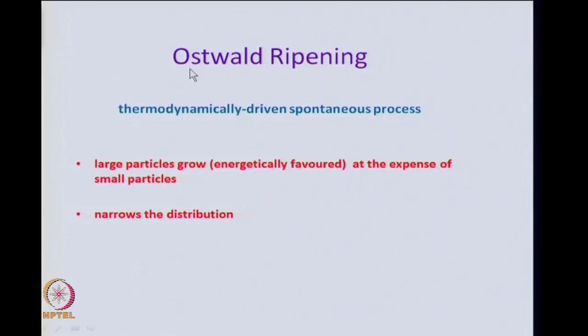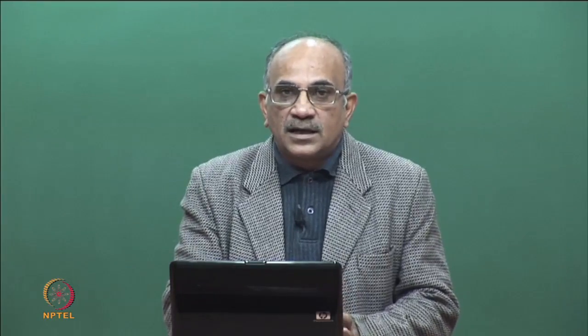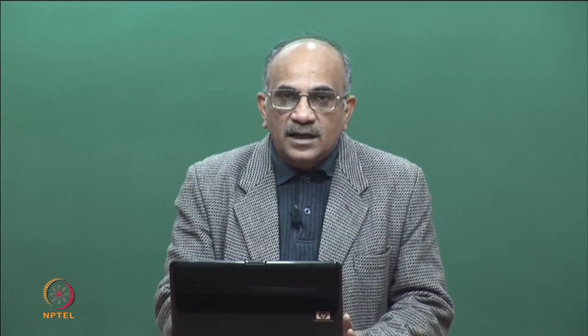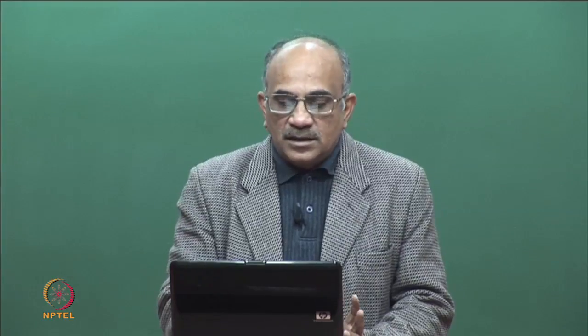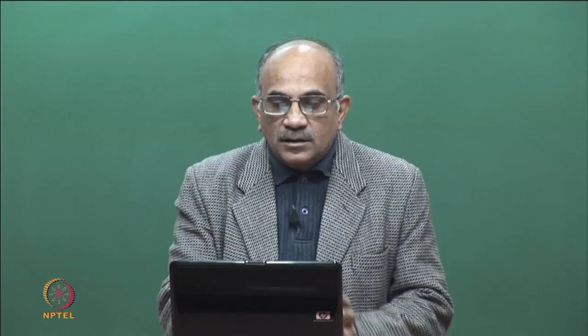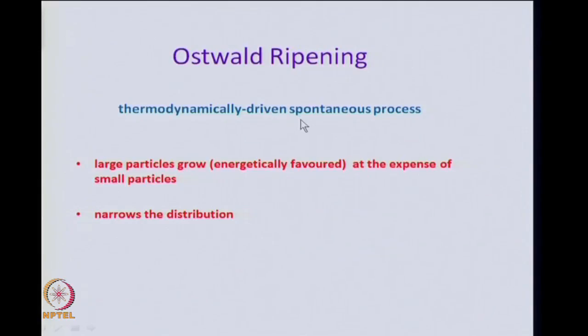And this is the Ostwald ripening process, and as I said earlier, this is a thermodynamically driven process, and it will occur spontaneously in any system unless you give some external input, external driving forces, which may be in the form of salts or other chemicals or some electric field or magnetic field. Then you can go to a process which is kinetically controlled and not the thermodynamically driven process, like the one guided here through the Ostwald ripening process.